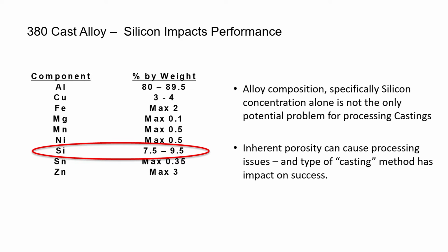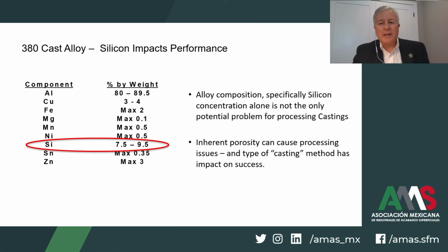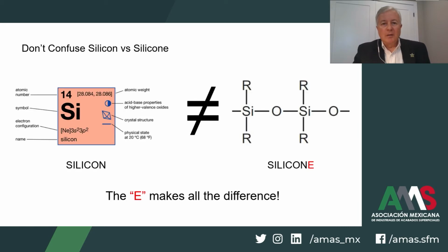Silicon is added to cast alloys for allowing better casting of parts, components, and for manufacturing complex configurations. Its concentration will vary depending on the type of cast alloy, but also the casting methods that are used to make the parts will also change the nature or the shape of the silicon at the surface. This, generally speaking, provides one challenge in surface finishing cast alloys that we must overcome. But remember, please do not confuse silicone with silicon. The E in the name does make all the difference in this case. Remember, silicon is an element on the periodic table, while silicone is a chemical compound. They are not the same.